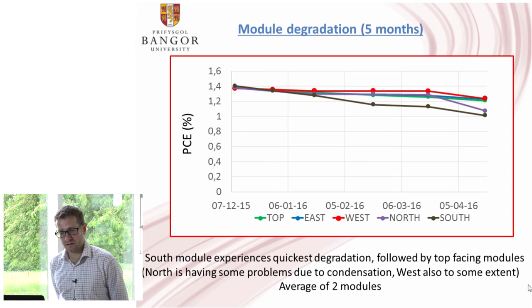So the other interesting thing we've been looking at is how the modules degrade on different sides of the building. We've seen some quite interesting trends. Overall, our south-facing module exhibits the greatest degradation. We think the reason for that is because it initially experiences the greatest irradiation. That sort of triggers a degradation which continues on for many months onwards. Recently, we've been finding the north-facing module actually experiences quite bad stability. And really the reason for that is the north-facing module experiences a lot of condensation, and the condensation has an impact upon the stability as well. So it tends to be our north and our south-facing modules that experience the poorer stability.